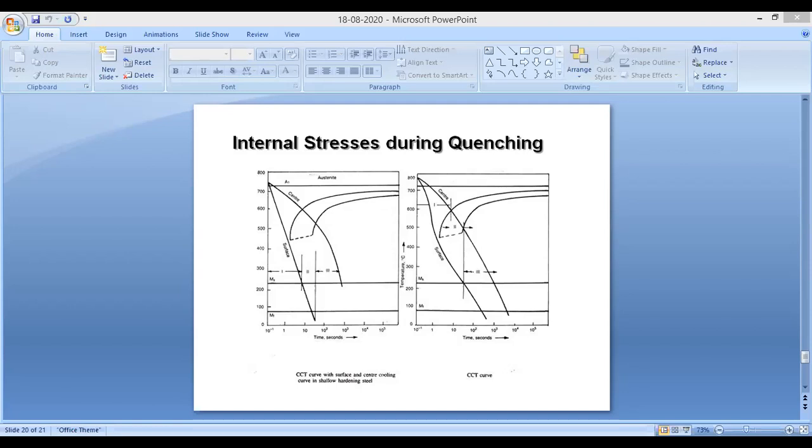In stage 3, as the center is thermally contracting, the surface, which is almost at room temperature, prevents the contraction as much as it should. Higher tensile stresses develop in the center, which is pearlite of relatively low tensile strength. The greatest danger now is to produce a tensile crack in the internal central part, but it cannot come to the surface because of prevalent compressive stresses in the surface.